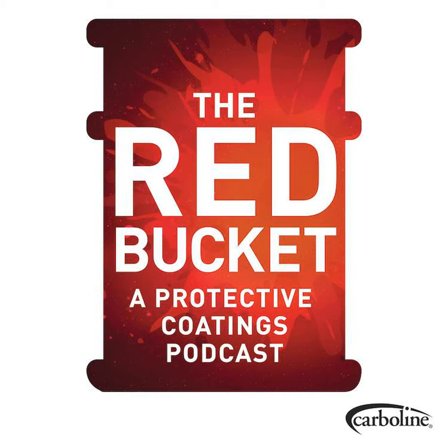Of course, every car is going to be different, and the amount of added work that you can avoid doing by using this product will be different case by case. Is this a pretty significant time saving if you run that over a fleet of cars? What kind of savings are we talking about here? You're eliminating an extra step in the process. You're looking at 30, 45 minutes to an hour to do those areas that are heavily corroded. So that's one part of it. The other is the consumption, having to mix and measure kits just for that particular process.